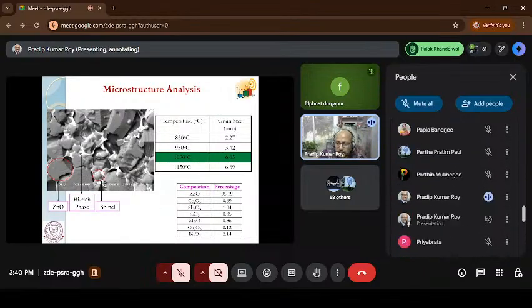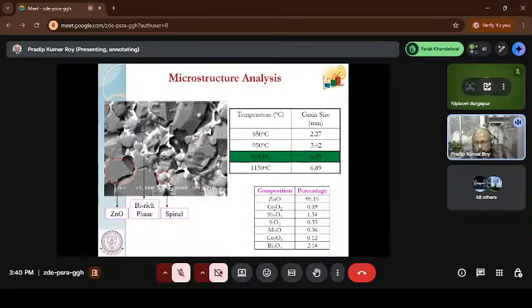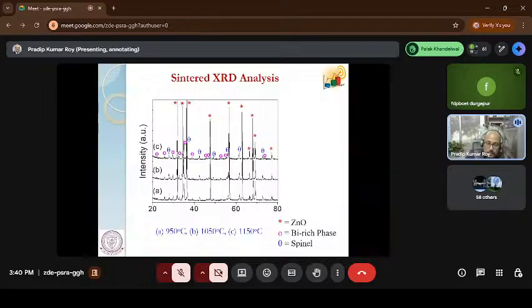So we have found the grain size around 6 micrometer. Sorry, it's not millimeter, it's 6 micrometer. And normally in industry, as I said, it is around 12 micrometer. By using this nano, it directly goes down to 6 micrometer. We have checked the compositions also, it is almost the same as what we have used. There is no kind of evaporation during the sintering process. We see the XRD phase also, there are no impurity phases. There are only three phases: the zinc oxide, bismuth phase, as well as the spinel phase.